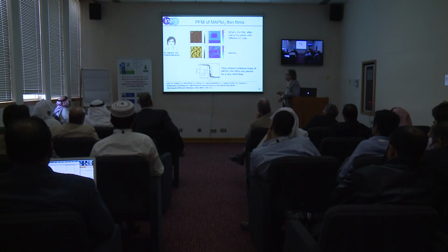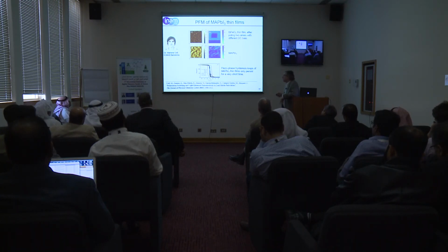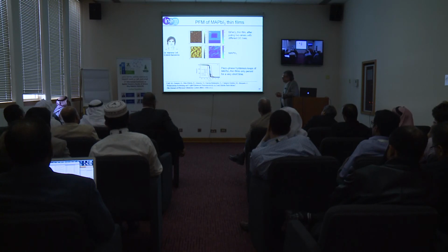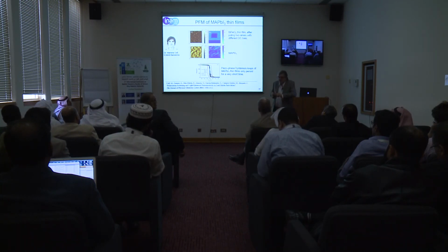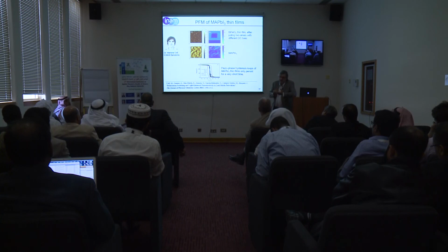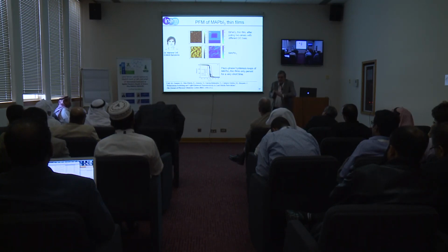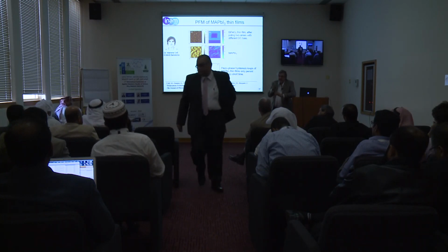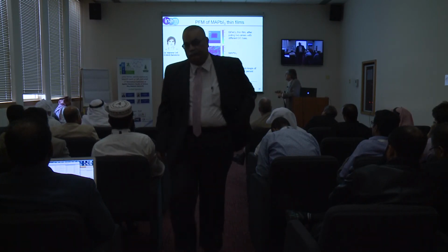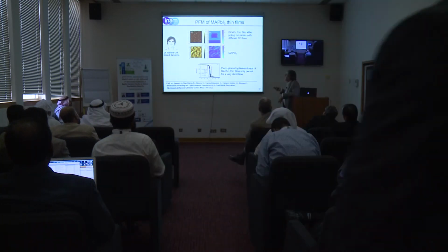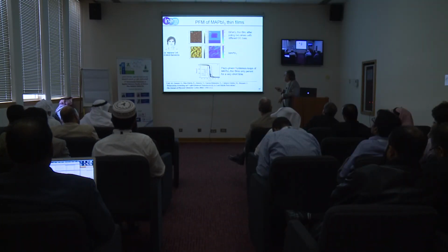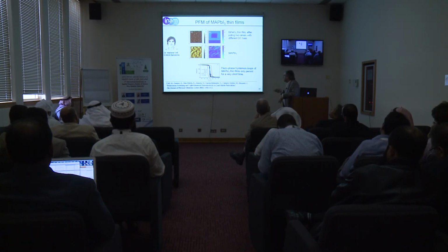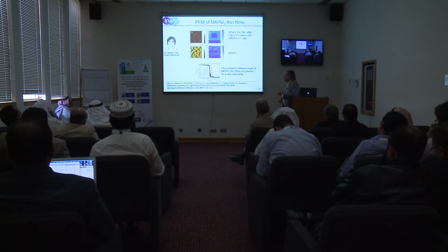So one thing we did explore was the possible ferroelectric property of the perovskite, because if it is ferroelectric, it can get spontaneous polarization in the absence of even an applied field. And normally this gives a very, very large dielectric constant. So we measured this with piezo phase, using AFM, you study the phase of polarization, and this has to be square to show hysteresis due to ferroelectric polarization.